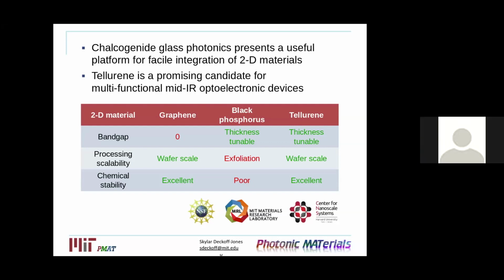Yeah. So, I mean, clearly graphene has had the most time to develop, and its production at a large scale is quite impressive at this point. So it's sort of large steps ahead of the other 2D materials, but I think largely it has that advantage just due to popularity. So if another material can be demonstrated to have physical material properties which warrant the additional research towards large scale processing and manufacturing, then that's quite promising, or could be promising. Again, because graphene does have its limitations, as for the example of photodetectors, its lack of a band gap is definitely problematic. But yeah, scaling up is always a challenge, especially with 2D materials.